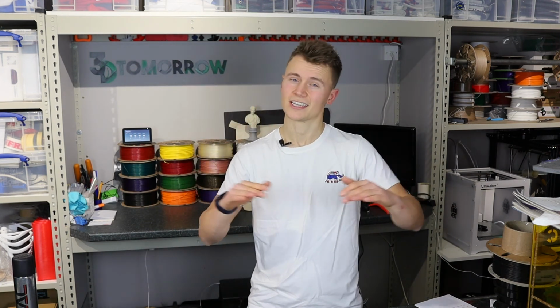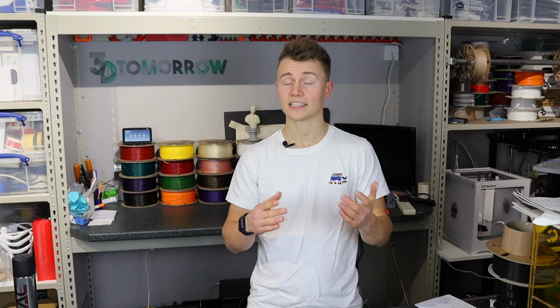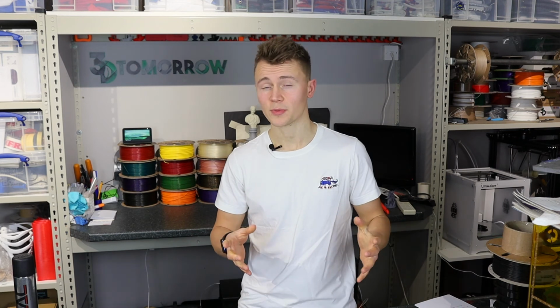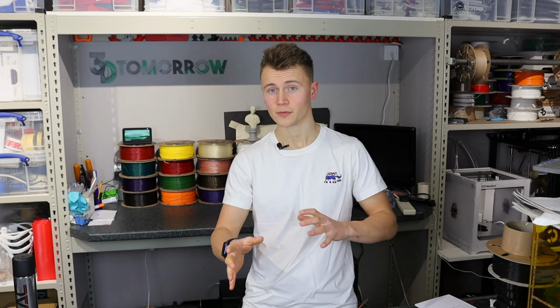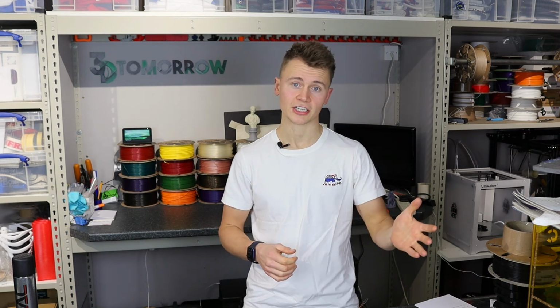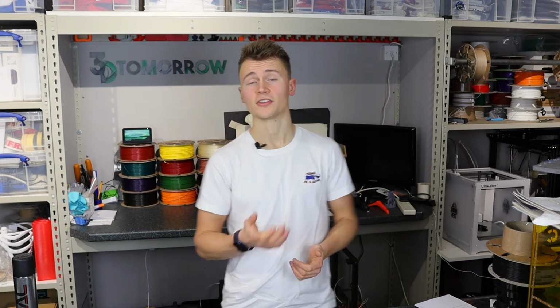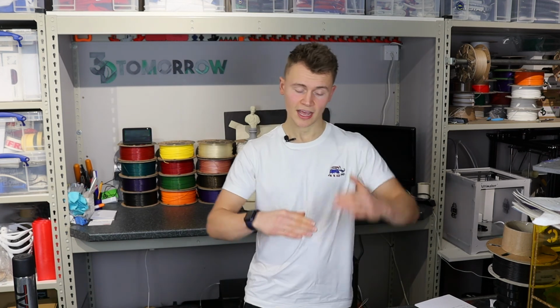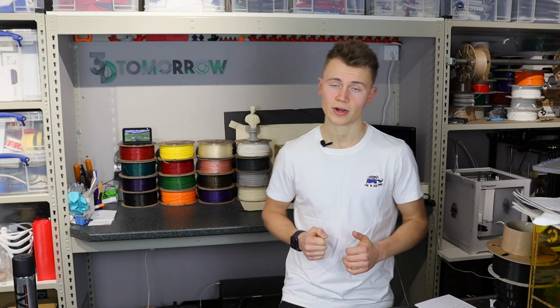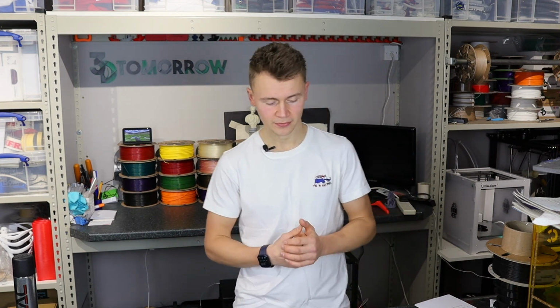The brim is just a little countermeasure in the corner and can generally do quite a good job at preventing this. One thing to note with brims is I find the separation distance really beneficial for getting the best of both worlds between improved adhesion but also easy cleanup. I use a 0.2mm separation, and that coupled with a good bit of bed squash ends up with an easy to remove brim that does its job as well.